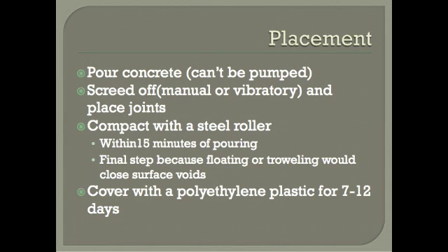The pervious section needs to be covered with a polyethylene plastic because the water is needed for the curing chemical reaction and would otherwise evaporate because of the large void content. Curing takes about 7 to 12 days, and the concrete should remain covered for that period of time.